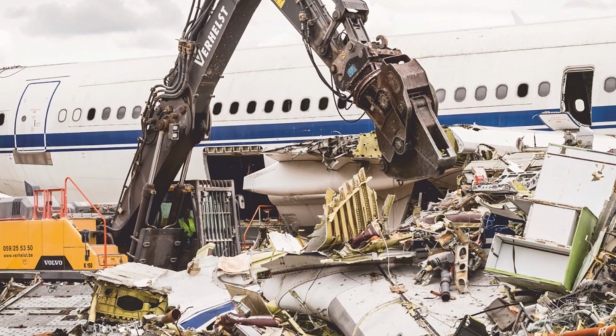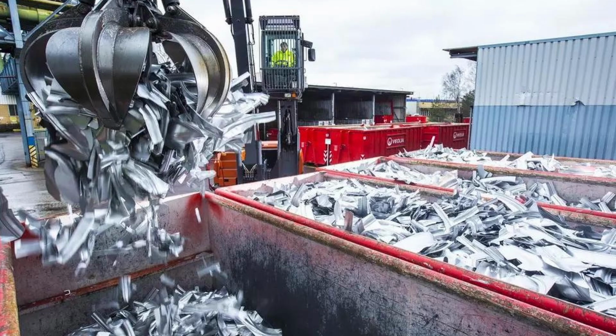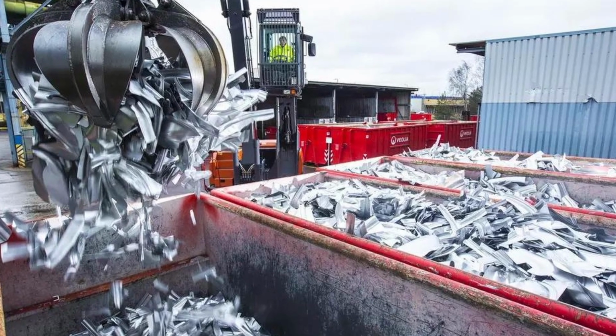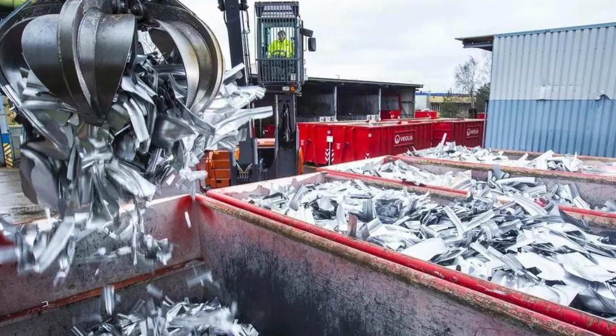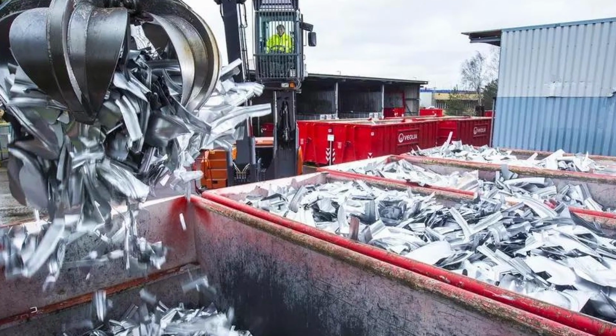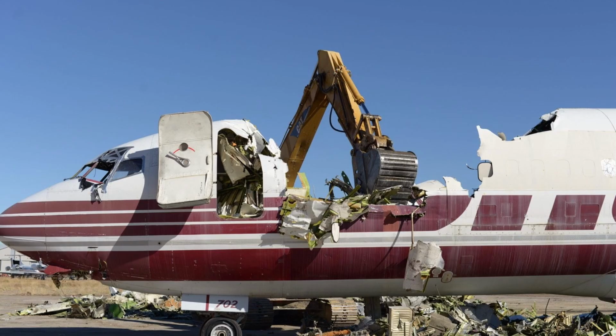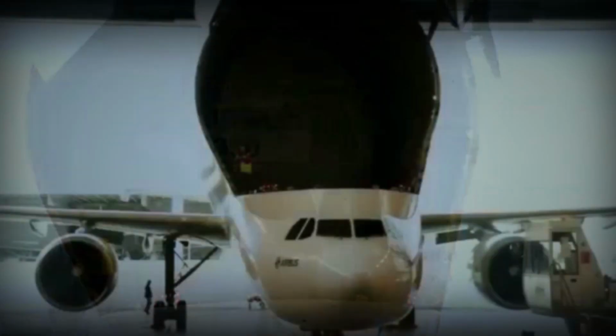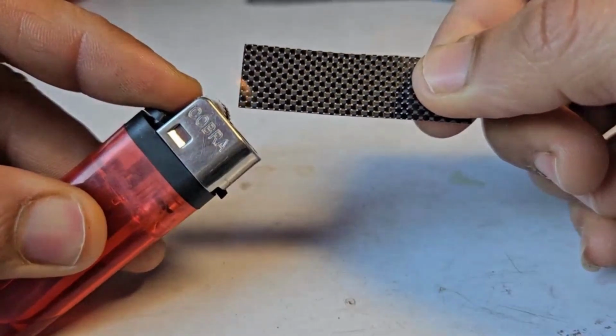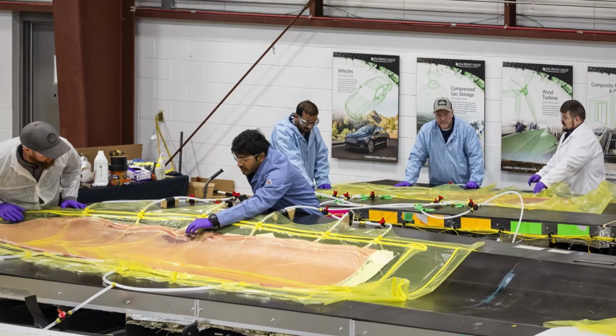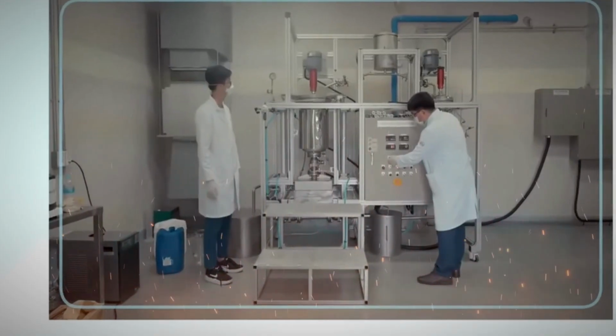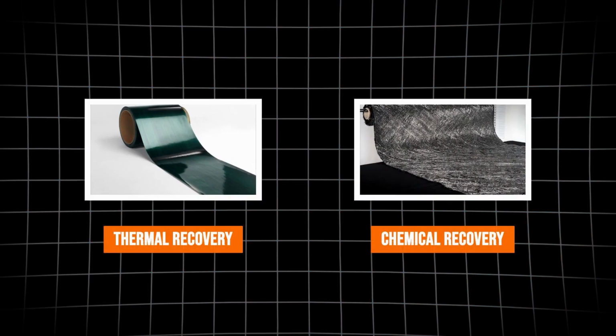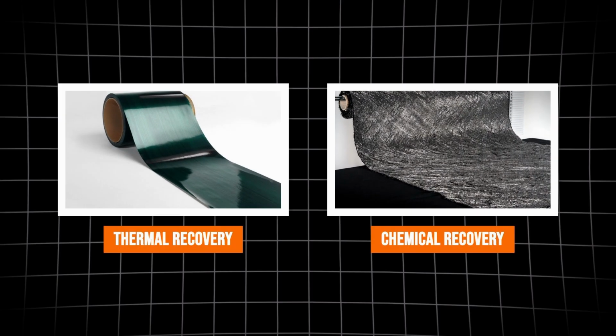Everything described so far works because the aircraft being retired today are built primarily from aluminum, straightforward to sort by alloy, melt, and reuse, at roughly 5% of the energy needed to produce virgin aluminum from ore. The industry consistently recovers 85 to 95% of a retired aircraft by weight, but the Boeing 787 and Airbus A350 are built from up to 50% carbon fiber composite. Carbon fiber cannot be melted. The resin bonds are permanent. Once cured, they don't reverse. Recovering the fibers means burning off or dissolving the resin, and both processes degrade the material beyond aerospace use.